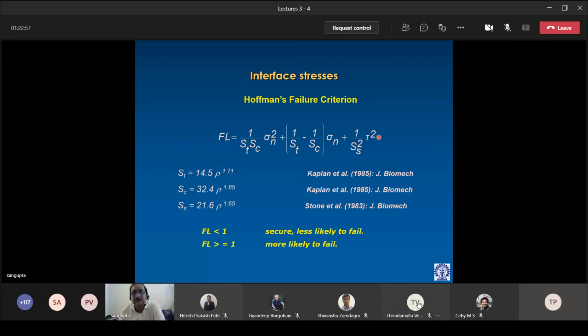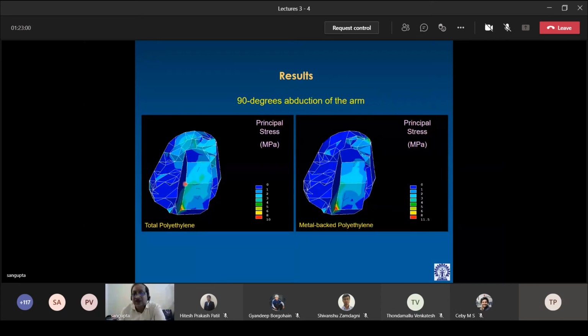Look at the results. So this is basically the principal stress distribution in the cement volume, or the cement mantle as we call it. Okay, so one side you have total polyethylene, the other side you have metal backed polyethylene. It is similar to some extent, more or less, but you can see that the stresses are a little higher, more distributed in the total polyethylene, where it is a little less distributed in case of metal backed polyethylene.